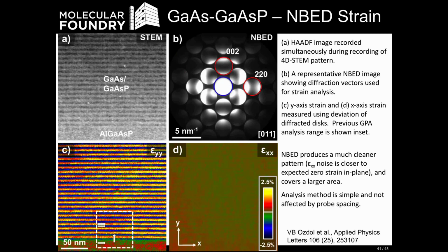And so by measuring the position of the two red disks, the 002 and the 220, with respect to the blue disk, we can make a strain map, shown in C and D, for perpendicular and parallel to our sample, respectively. This time, though, our field of view is significantly larger. You can see the scale bar is 50 nanometers in C. The white box shown is the size of the atomic resolution strain map shown in the previous couple slides. So we've increased our field of view by a factor of 10, and there's actually almost no limit to this. We can scan over as big an area as we want.